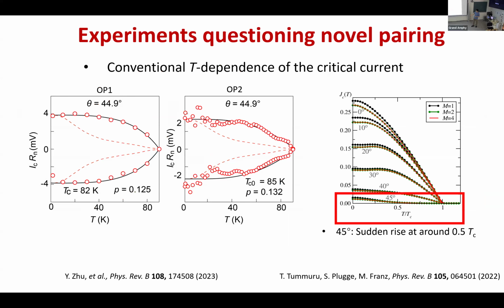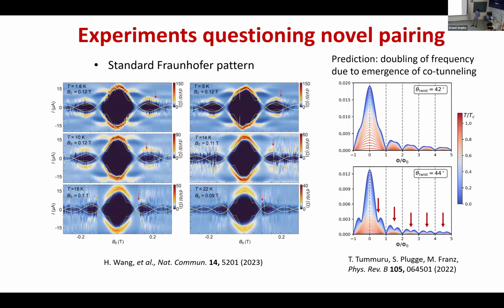So now let me show something against this picture. First of all, we tried many samples, and we could see that the critical current has quite conventional behavior, not as theoretically calculated for this d+id. With d+id higher order pairing, the temperature dependence of the critical current should be different, but it's not the case. We also checked the Fraunhofer pattern, and we don't see this h/4e appearing when you change the temperature.